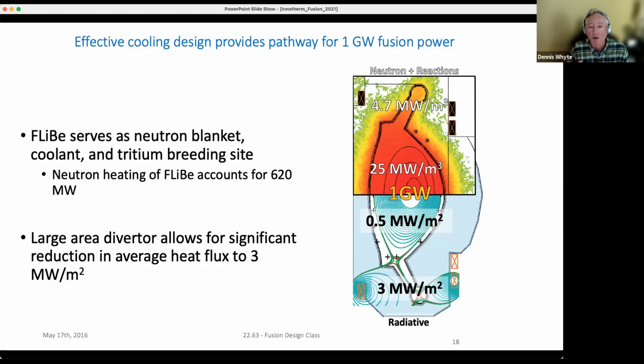And what you're seeing is a cartoon from a volumetric point of view. On the top is that it's making about 25 megawatts per cubic meter fusion power in the core plasma. And what this results in out in the blanket is an average loading of around 5 megawatts per cubic meter in the salt. But as I told you before, other parts of it have to do with surface heating. That's on the bottom. And there we get a global level of around 0.5 megawatt per square meter. And a concentrated part in the divertor, where we actually intentionally siphon off the plasma, it's more like a surface heat flux of around 3 megawatts per square meter.